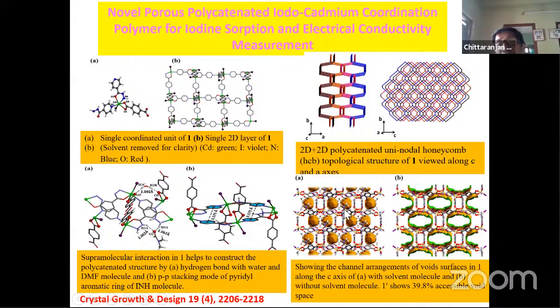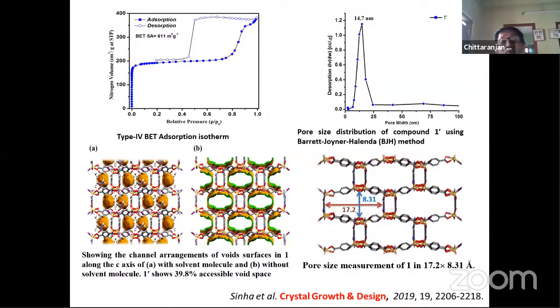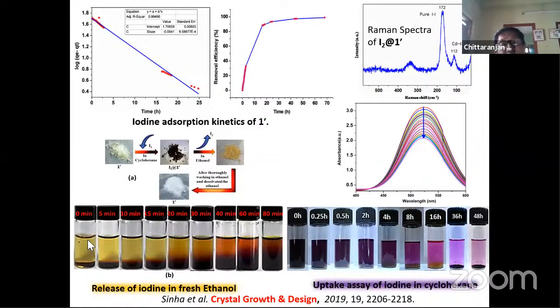On heating, these molecules are removed, and the cavity becomes free. And this cavity is now available to absorb some molecules or ions. And one such absorption is of iodine. It absorbs iodine, you see. You take an iodine solution in cyclohexane and add the crystals, and then these crystals absorb iodine, and you see after 48 hours the supernatant becomes almost clear, and the crystals are colored. Thus this crystal absorbs iodine, and this iodine which is absorbed in the crystal cavity is also removed on heating or treatment with ethanol.